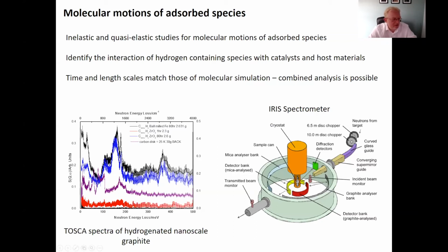So this is a TOSCA spectra of hydrogenated nanoscale graphite, increasing the amount of hydrogen on it through treatment of that material. In the red one, this is hydrogen on ZrO2. The blue one is hydrogen on ZrO2 that's been exposed for 80 hours. And the black one is ball milled and then exposed for 80 hours. And so these peaks that appear here in the inelastic spectra correspond to hydrogen bound to the surface of carbon nanoparticles. And the energy of these peaks is a feature of the nature of that binding, whether you're forming hydrogen bonds to graphitic hydrogen or aliphatic hydrogen, or graphitic carbon or aliphatic carbon.